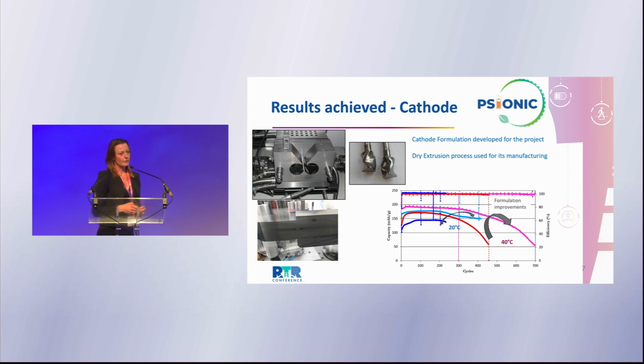On the cathode side, we have worked both on the processing and on the cyclability of the material. So the first step was to prove that we were able to extrude the NMC material together with the polymer electrolyte, and to develop the catholyte formulation, because of course we didn't want to put PEO directly in contact with NMC. So we have developed the catholyte formulation and extruded it, and we got promising results with a model electrolyte that was not PEO based.